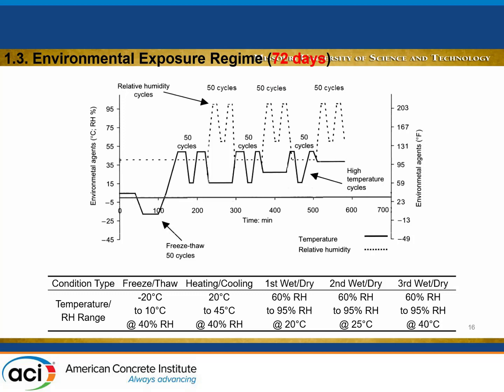So what we have over here is 50 cycles of plus or minus, so we move between minus 20 to 10 Celsius, and then another 50 cycles between higher temperatures, 50 cycles with relative humidity, and then temperature, humidity, and so on. So the total, as I mentioned, is 72 days or 350 cycles of loading.